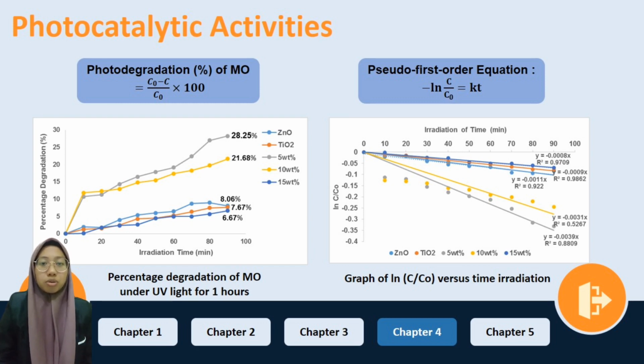When the doping of titanium dioxide exceeds 5 weight percent, a decreasing pattern in the photocatalytic activity can be seen. Previous studies have reported that a higher content of titanium dioxide dispersion could have a negative impact on wastewater treatment because the particles can block the UV light path, resulting in a reduction in degradation efficiency.